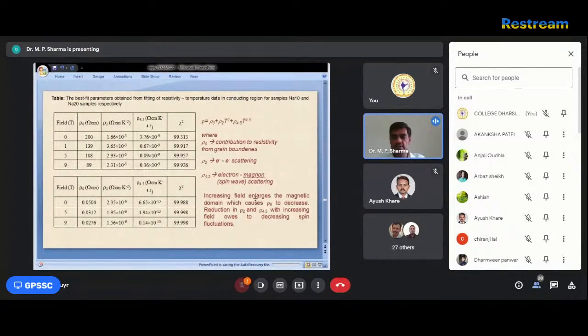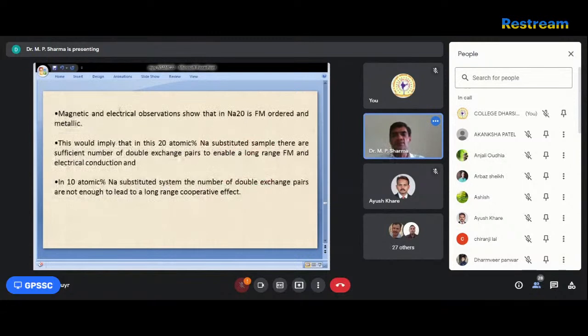concluded that increasing the field enlarges the magnetic domain, which causes rho 0 to decrease. The reduction in this one is because increasing the field also decreases the spin fluctuation. When you increase the field, the fluctuation between the spins decreases because the field is very high. So now magnetic and electric observations show that sodium 20 is FM ordered and metallic. This implies that in the 20% sodium substituted sample there are a sufficient number of double exchange pairs to enable the long range FM ordering, which is our aim to observe.